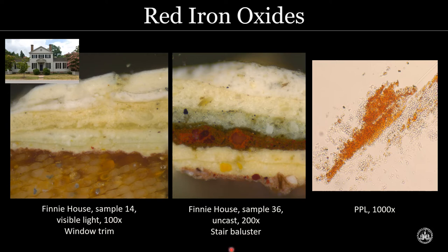Now in this center image, the primer is a bit thicker and we can see these chunky, rich, deep red iron oxide particles. But the matrix is actually kind of pink because there was a lot of lead white mixed in with this pigment. And I thought I would also point out that the paint applied on top of the red-brown primer was a buff or tan color paint, made by adding yellow iron oxide to a lead white. So you can see this really beautiful bright yellow iron oxide particle in that lead white matrix.